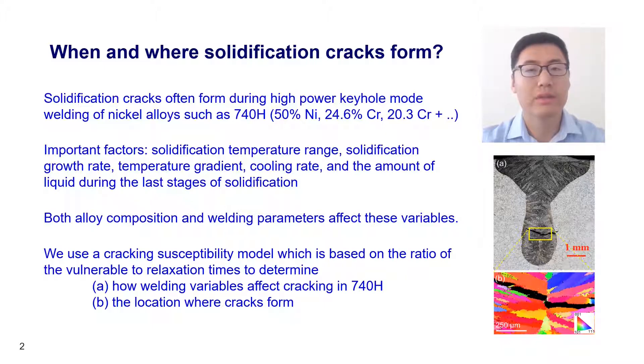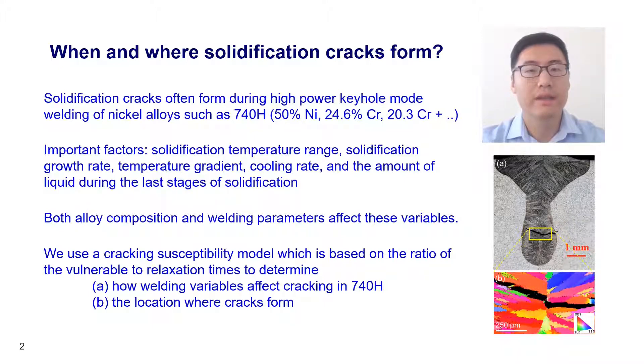Here, we used a cracking susceptibility model, which is based on the ratio of the vulnerable to relaxation times, to determine how the welding variables affect cracking and determine the locations where cracks occur during high-power keyhole mode laser welding of nickel alloy 740H. We explain this model and its implementation in the next slide.